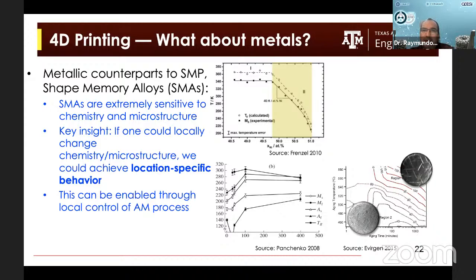In the case of shape memory alloys, they are extremely sensitive to changes in chemistry, right? So for example, here I have a plot of the transformation temperature of nickel titanium, this is the nitinol alloy, as a function of nickel amounts.